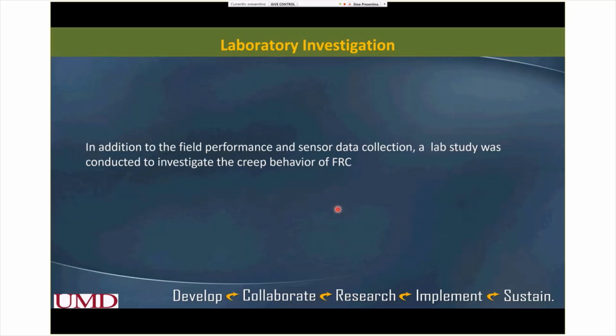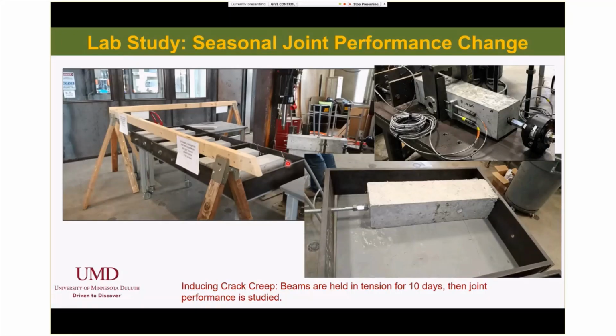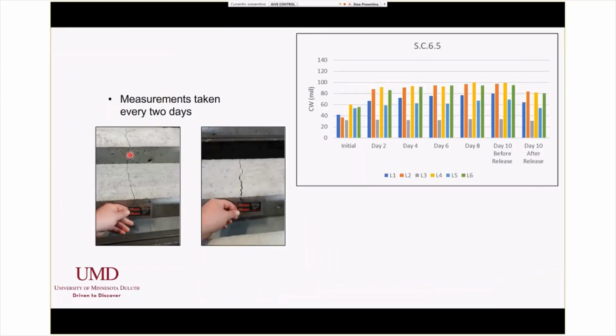This is a little bit of an additional thing that we did not have in the proposal, but one of our graduate students worked on it, so we'll include it in the final report. As we know, a lot of researchers noted that the synthetic fibers we use in pavement are prone to creep. So in this experiment, we induced crack creep. What is crack creep? We actually cracked this beam. We induced a crack.